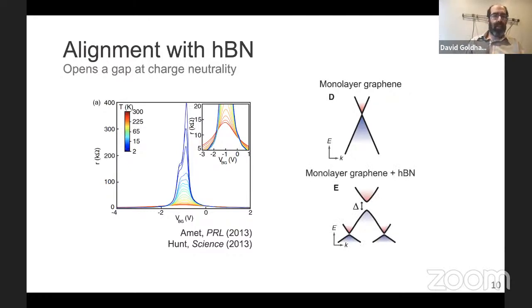So just to give you a somewhat concrete picture of what's going on in this complex stack, here's a cartoon of just one layer of graphene, hexagonal lattice. Now let's put another layer on top, and here we get Moiré, which I think you've been seeing a fair amount during this summer school. And now we're adding something like what Tim Kaxiras mentioned near the end from Zoe's work. We add yet another layer, which in this case is the boron nitride. Since we know the twist angle from our electrical measurements, we can actually say how it's aligned.